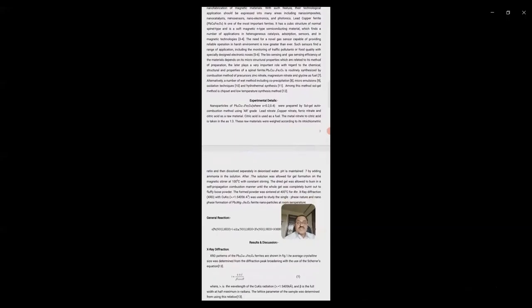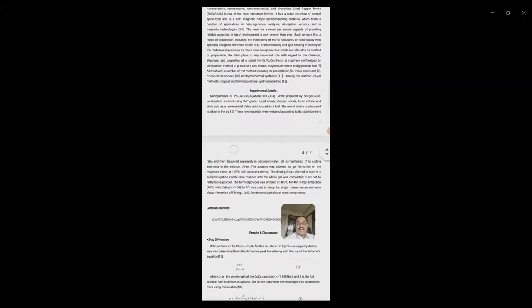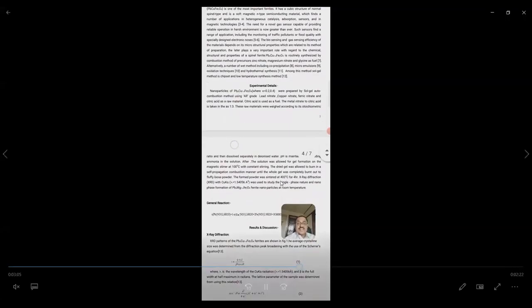The raw materials were weighed according to the stoichiometric ratio and then dissolved separately in deionized water. pH is maintained at 7 by adding ammonia to the water. After the solution was allowed to form a gel on the magnetic stirrer at a constant temperature of 100 degrees centigrade, the dried gel was allowed to burn in a self-propagating combustion manner until the whole gel was completely burned out to be fully loose powder. That powder was sintered at 400 centigrade for 4 hours.